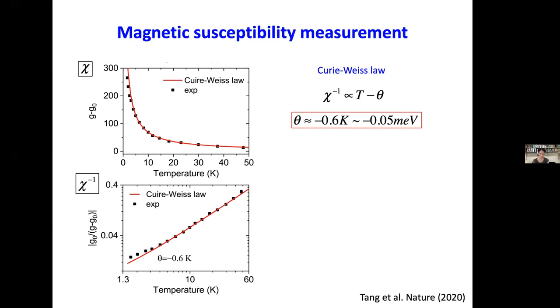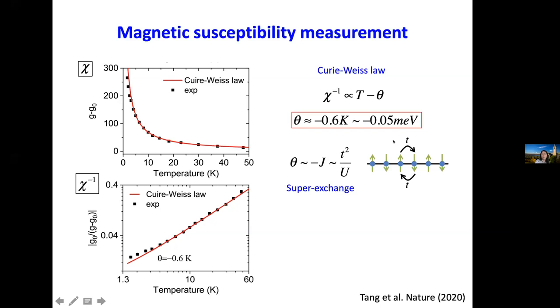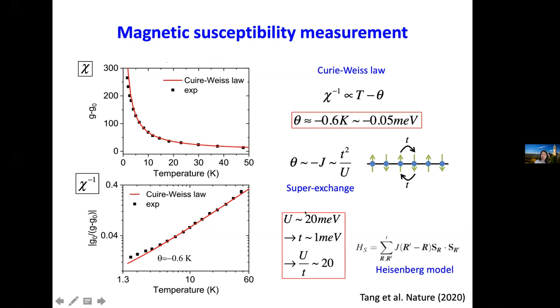And in the picture of superexchange for a Mott state, this temperature gives the magnetic coupling constant J, which is t squared over U. And we already know that U is on the order of 20 meV, and J is 1 Kelvin. That gives t to be on the order of 1 meV. And this value is in good agreement with some DFT calculations.